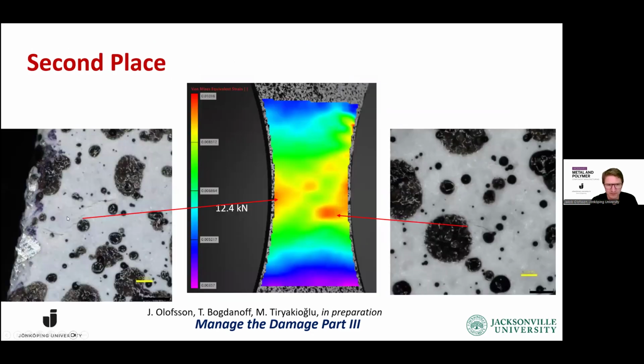We also can see then in the second place, runner-up, this that didn't cause a failure but had a high strain concentration. We can see that there are cracks on the surface, and you see that already in the paint. And as we saw before, we know that then also means that we have oxides at these places. To the right there's a combination of the visible damage that was seen in the X-ray, but also the extending hidden damage, which has clearly separated and caused these cracks to appear, but not been the winners in the race to the failure.